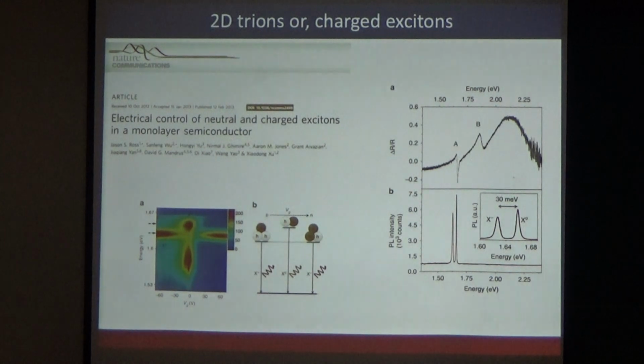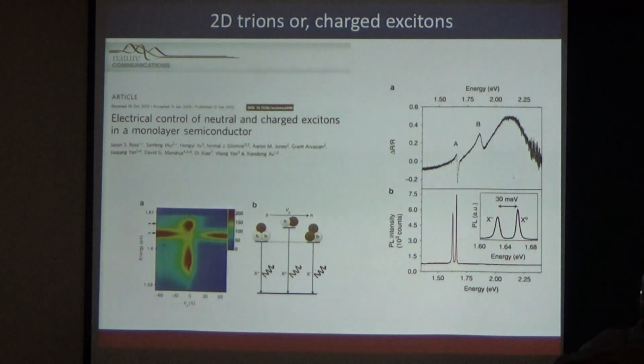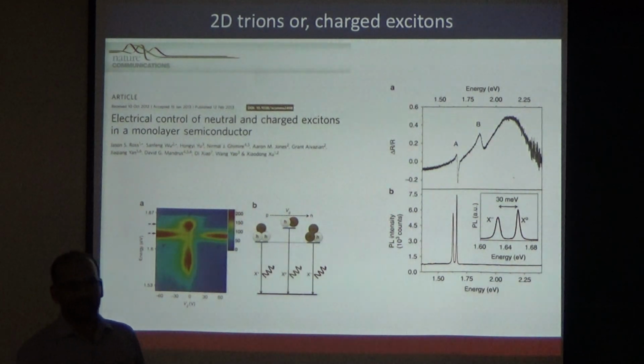Okay, now the other interesting species that exist in this material is that you can also form a bound state of an exciton with another electron. Suppose I have an exciton gas, and if there are free electrons, if I introduce some doping, either electronically or chemically, those free electrons will basically form a bound state. Now these bound states are also stable. It isn't just like a hydrogen ion. The hydrogen ion is a very stable bound state, and this charged exciton that I am talking about, a bound state of exciton and electron, is also a very stable bound state with a binding energy of 30 milli-electron volt.